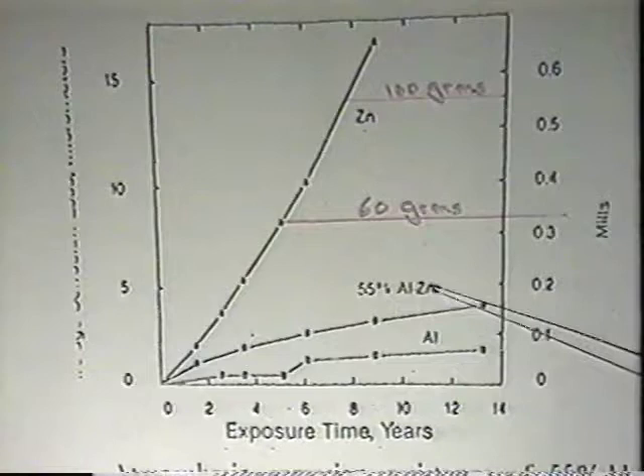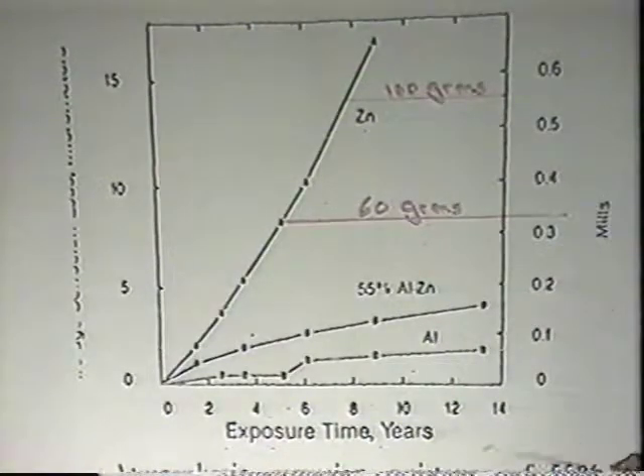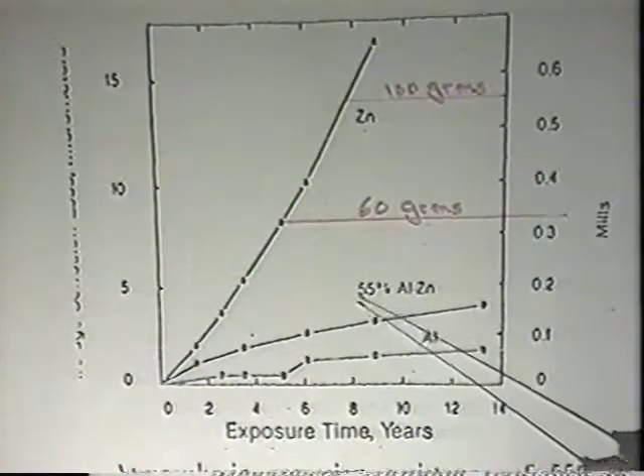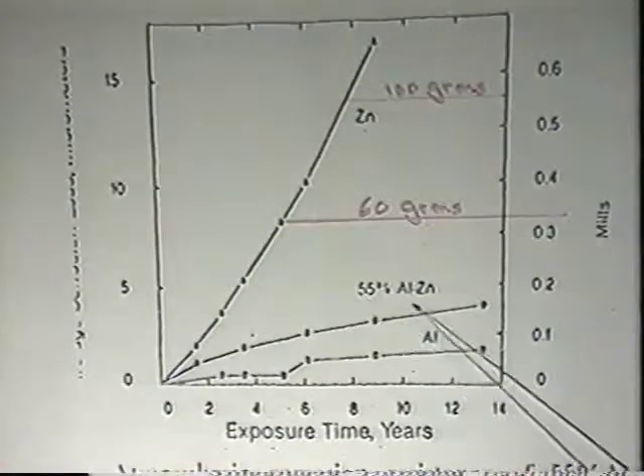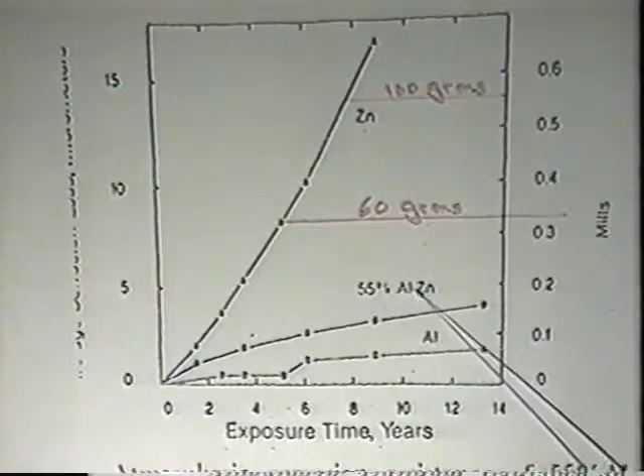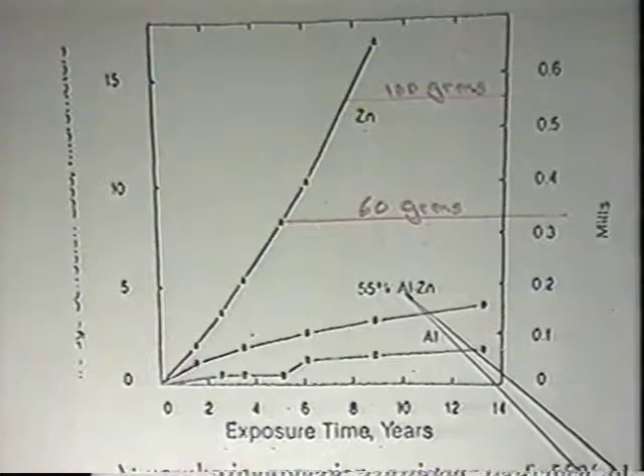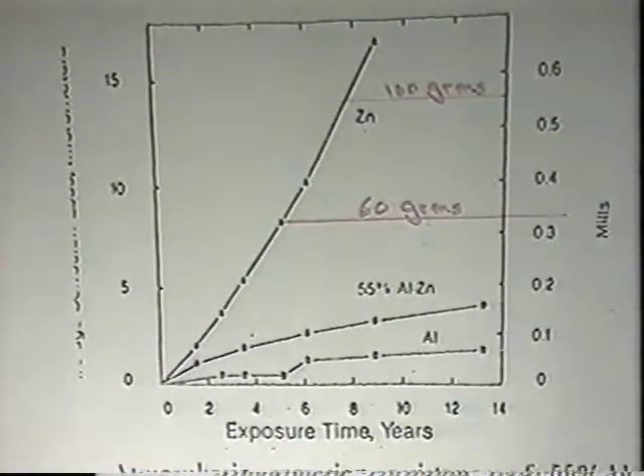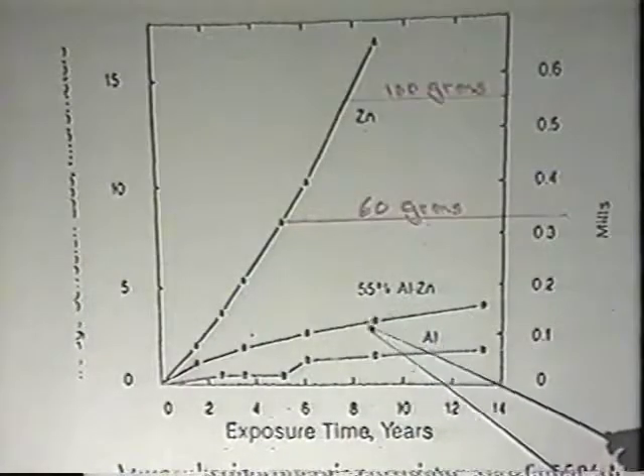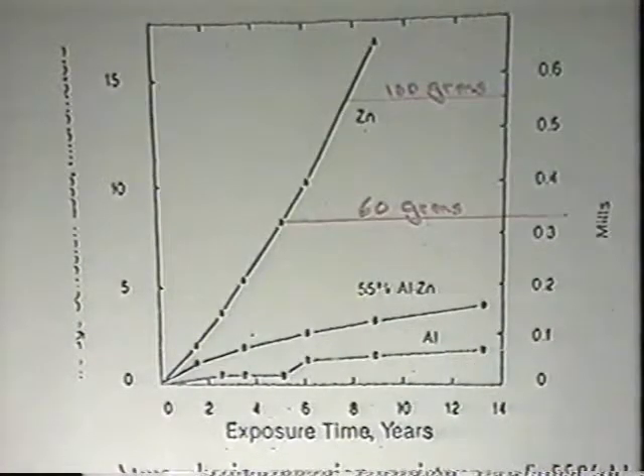And also on here, I talked about those barrier type protections, the aluminum coatings. You can see what a good job they do as far as corrosion resistance at a lesser coating weight. You get very good corrosion resistance. This product here is called Galvalume. We make it down at our Sparrows Point plant outside Baltimore. It's about 55% aluminum, the rest being zinc. Very good corrosion protection, kind of tough to paint and weld, but for guardrails, things like that, a very good product. Will last out there for years and years. So again, just to illustrate different points here.